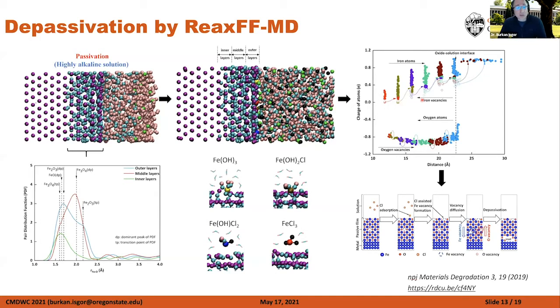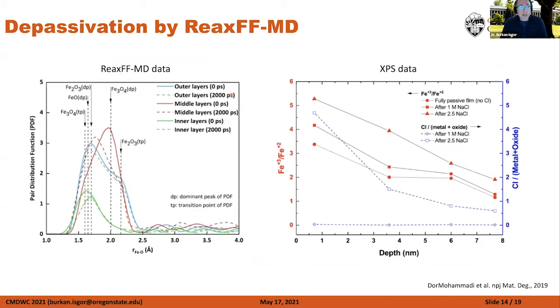Again, these simulations, as I said, are very time limited. We cannot do these simulations for very long periods. We're talking about very small time periods here. So we cannot show the defect formation at the metal passive film interface, but it gives us a hint that because these iron vacancies are moving in that direction, there is a suggestion that a model like the point defect model might be the more appropriate way of describing this. And we did not see any chlorides penetrating into the passive film in these simulations. As you look at the pair distribution functions, you also confirm that shift from Fe2 to Fe3 structure, which was also very useful.